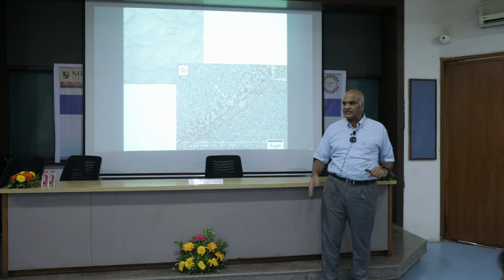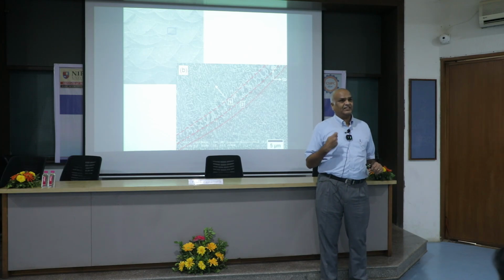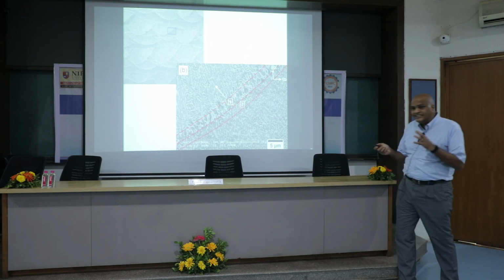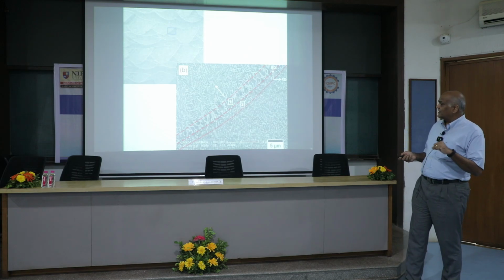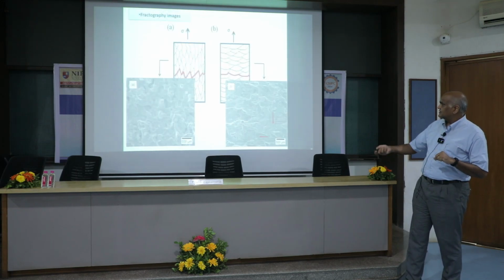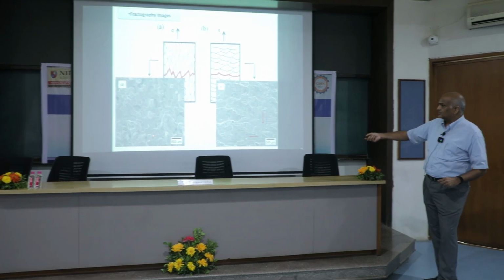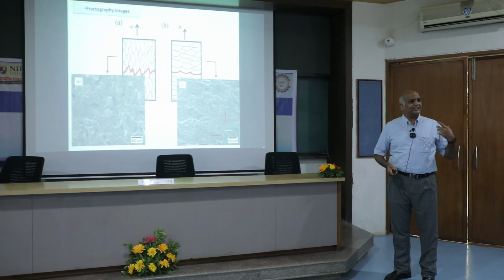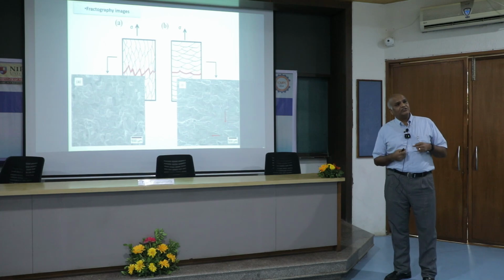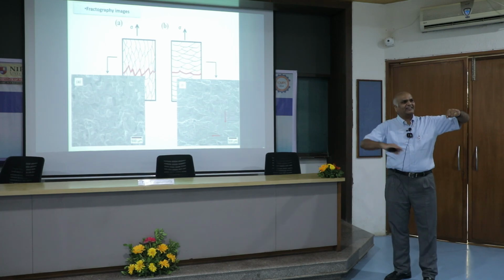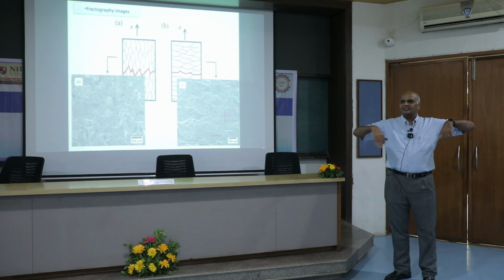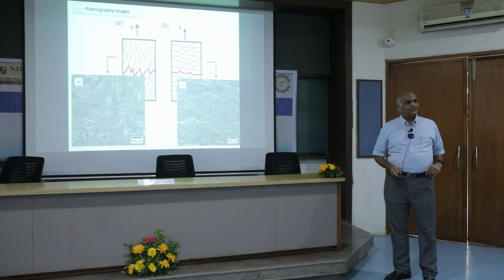So the cracks also, when you have a much more tortuous path, you have to spend a lot more energy. Nature knows this, and that's why in a lot of structures like our bones, there are a lot of crack deflectors built in, right? So when we 3D print the structure, there is this mesoscopic structure which deflects the crack, and you can see it in the fractographs. So there is quite a lot of crack deflection. And when they deflect, you have to spend more energy to keep the crack propagating in the mode 1 direction, and that's why fracture toughness goes up.